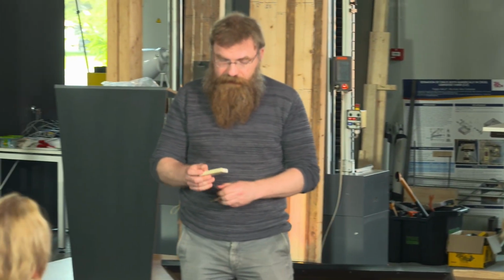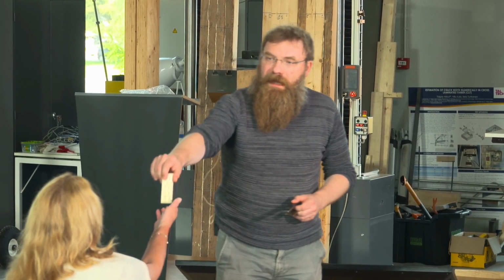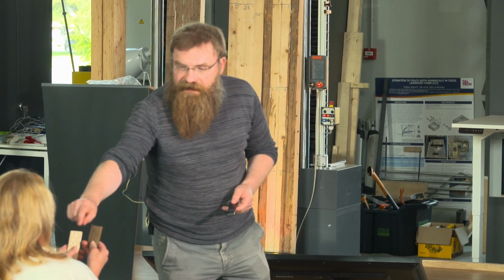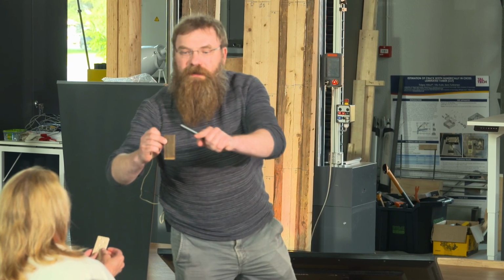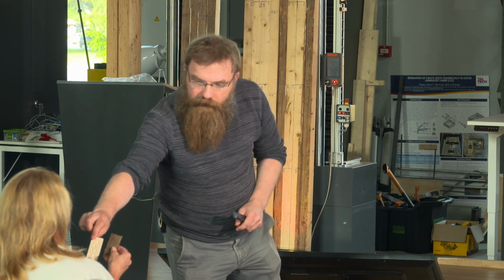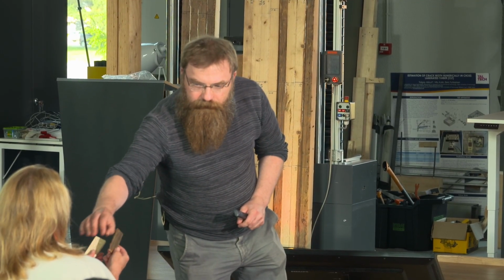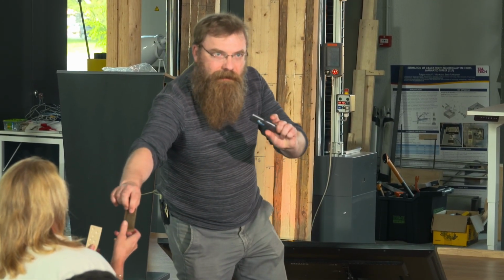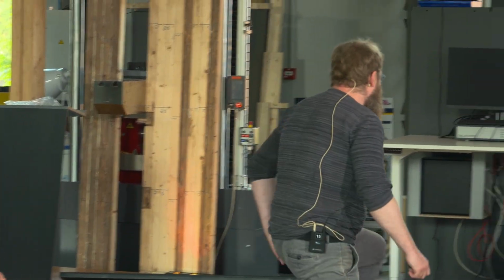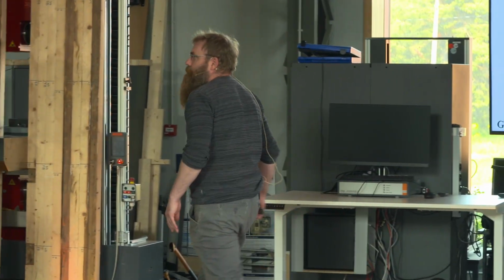So this is the sample of aspen, which is not densified. And this is the same material, basically it was the same size, a sample was just cut off. But basically the aspen, the size of it should be like that, but after densification we get a little slice of it. So we densify it to densify 80% of it. So the material amount left is like 20% around that. But this material now is very much stronger.